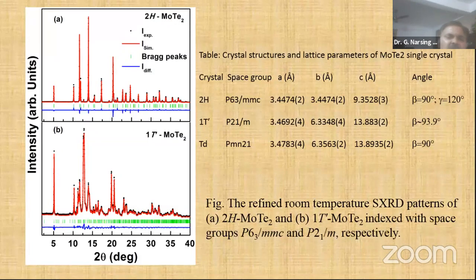Okay, you can see clearly here, is it not? The peak positions are different and the total number of peaks is also different. This one is a hexagonal structure and this is a monoclinic structure. This one is a less ordered structure, and this one is a more ordered structure, we can say. So this is 1T prime, and this one is the 2H material.